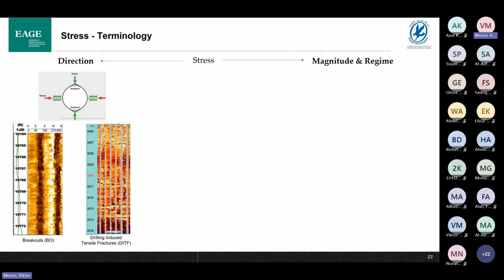For this purpose, we can run image log in a vertical well. If we observe the breakouts, this is an indication of the minimum horizontal stress, and if we observe the drilling-induced tensile fracture, this is the azimuth of maximum horizontal stress. For Kuwait, regionally, the maximum horizontal stress direction is 45 degrees northeast, and it's pretty much constant for Cretaceous and Jurassic formations in all country.